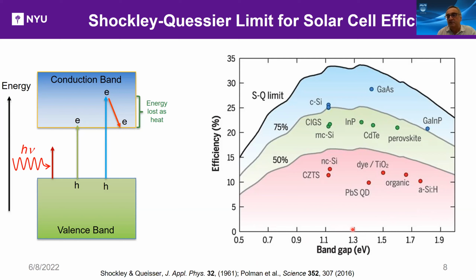And it turns out that the maximum, the optimum, is around 1.1 to 1.3 eV. And it's a pretty broad, forgiving maximum. And crystalline silicon is right smack in the middle of it. So it's nature's gift to humankind. And you can see here various other semiconductors and technologies and where they sit with respect to their own Shockley-Queisser limit. Those are the champion efficiencies. So crystalline silicon is somewhere around here at 25, 27%. And it's approaching the natural limit.